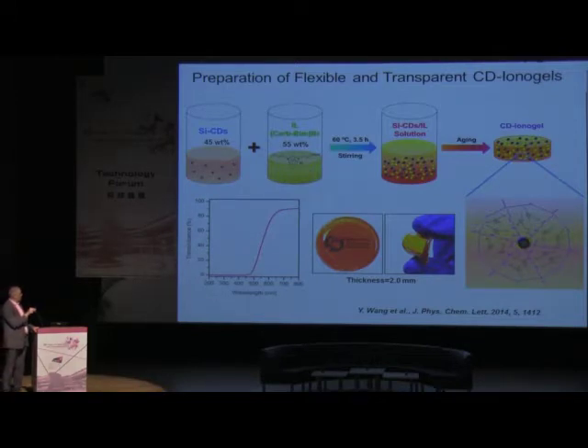First of all, we produced composite materials, which we call carbon dot ionogels. So we mix a solution of carbon dots with ionic liquid of some particular formula. We age them for a while, and then we get such large area samples. The thickness here is 2 millimeters, and the size of the sample is as shown, and we can make it even larger. These are essentially flexible pieces of plastic where we embed carbon dots at a high concentration.